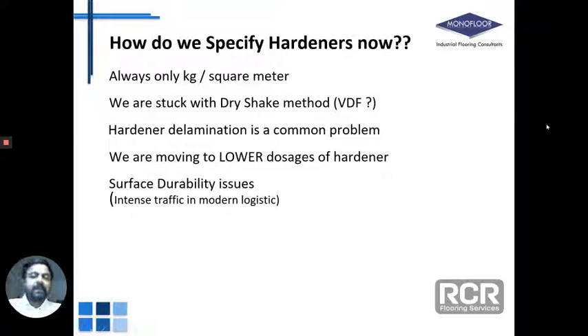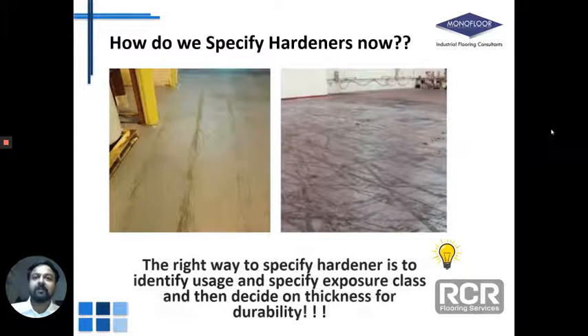So typically, because the thickness of the hardener layer is going down, the durability of the surface also becomes a question. Particularly when you have intense traffic in a warehouse scenario, you will have issues like this, when the top layer is just lost to continuous abrasion that's happening on the floor.